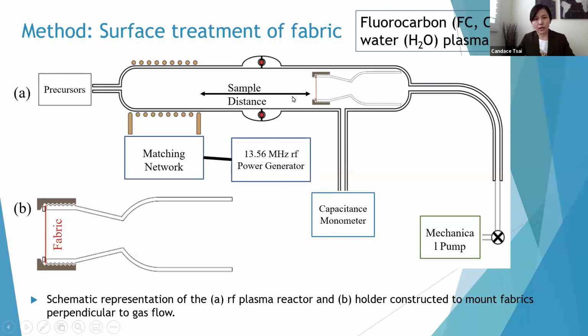This is the setup where the treatment was conducted, in this chamber, which is called a plasma treatment. We treat the fabric using fluorocarbon and also water. The fluorocarbon makes the surface become more hydrophobic, and the water treatment makes the surface become more hydrophilic. We mount the fabric here, located right over here. It's a pretty small piece, probably about 5 centimeters in diameter. Each time we coat the fabric about this size.